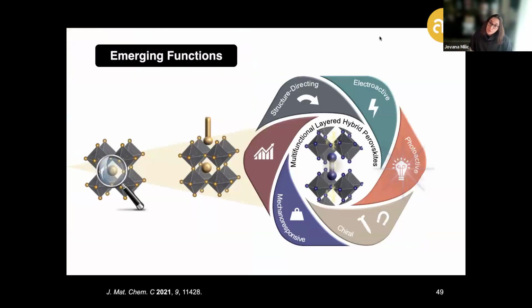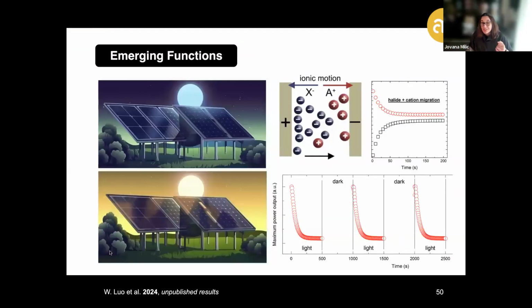This importantly opens a new perspective for tailoring these systems in response to alternative physical stimuli, triggered through changes in the organic component, including light as a stimulus. This offers the possibility to design smarter solar cells that are more adaptive to different light intensities or day-night cycles, involving control of ionic motions that can be accelerated in response to light or bias, with a certain reversibility of the ionic motion in the dark responsible for recovery of device performance when exposed to darker conditions or reduced light intensities.